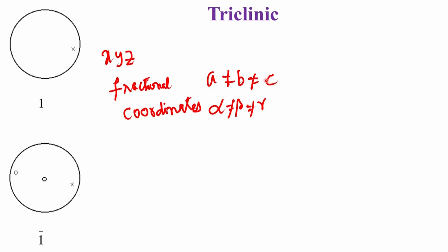This is a very important point, because when we talk about the coordinate system in a triclinic system, we should not assume that the x, y and z are coming from a rectangular coordinate system. That means the 90-degree angle is not there in this system. So, particularly people who do energy calculations and theory calculations based on this kind of information should convert the x, y, z to the proper set of coordinates before they use their theoretical approaches, because most of the theoretical approaches assume the system to have 90-degree angles, and A, B and C will then correspond to x, y and z axes.